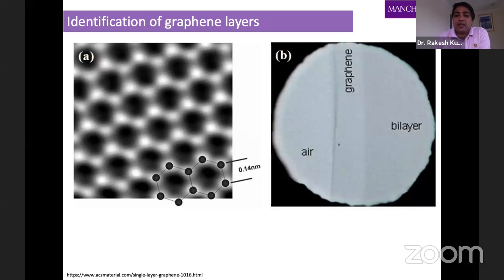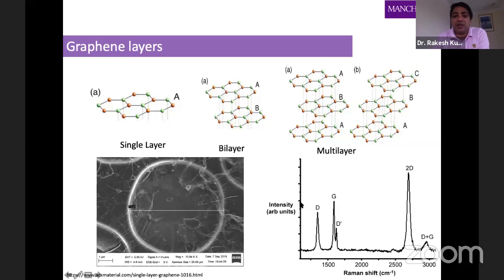But we can easily identify graphene under a high resolution microscope if graphene is transferred onto silicon oxide with a specific thickness. Mostly, if the thickness of the silicon oxide is 280 to 300 nanometer, then from the contrast of graphene and silicon oxide, you can identify even a single layer, a bilayer, or multilayer graphene. So these are the tools that we use.